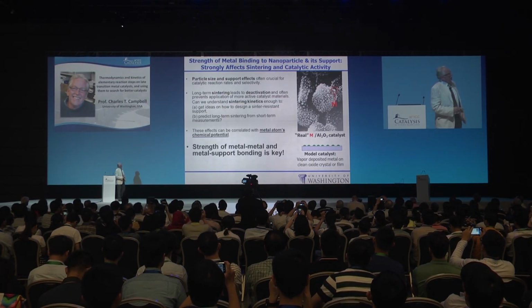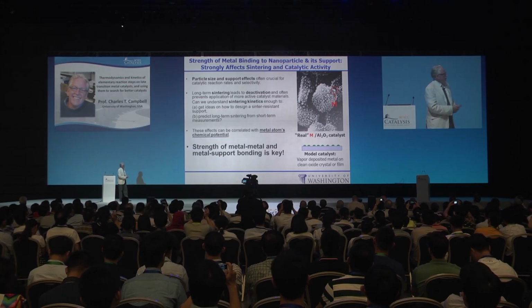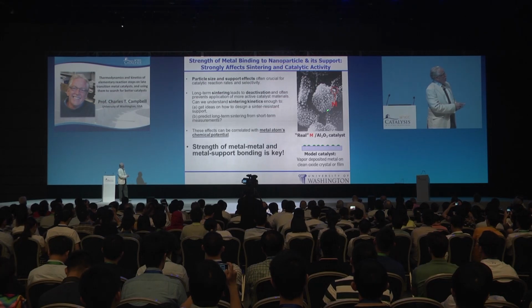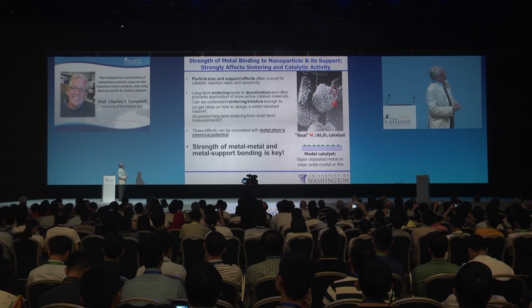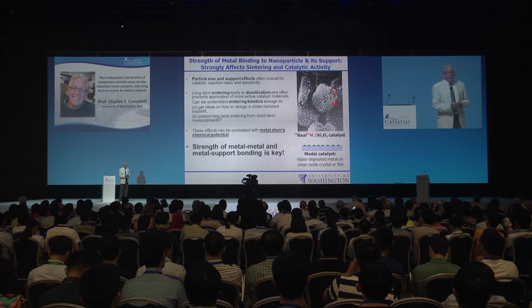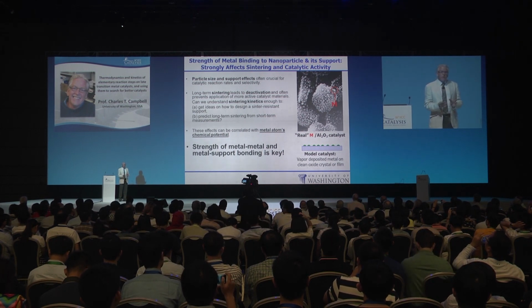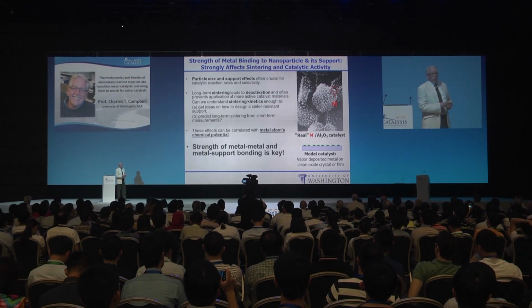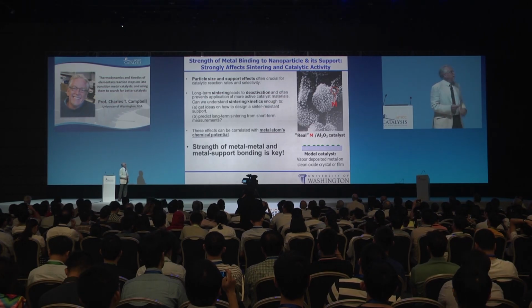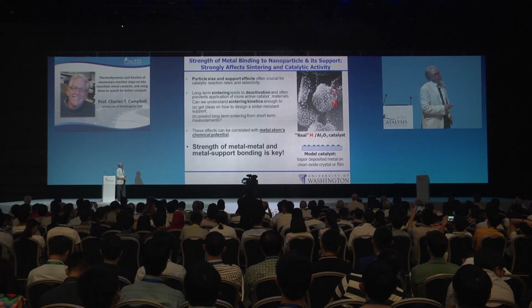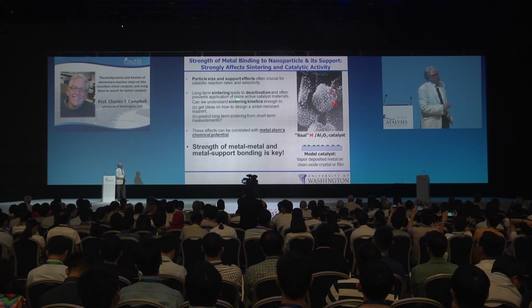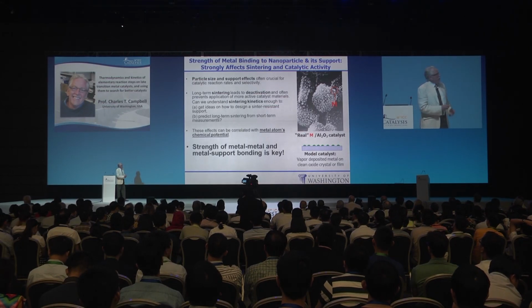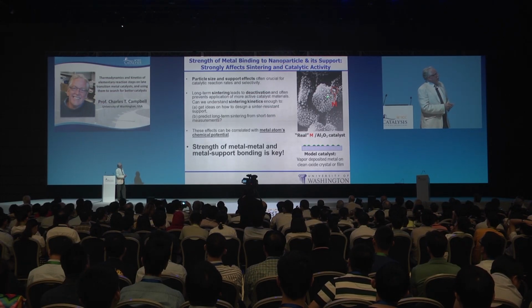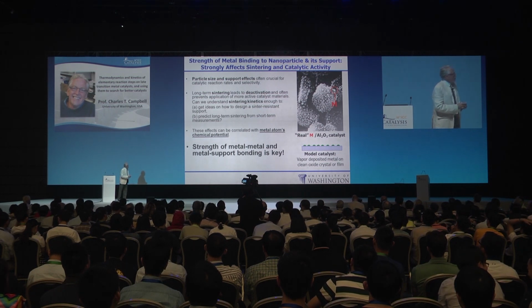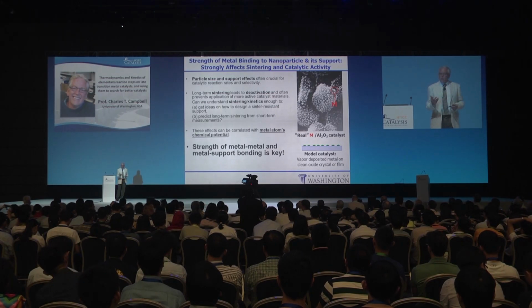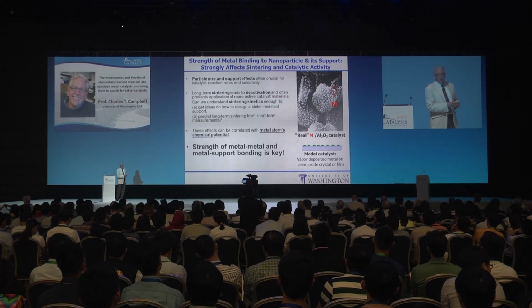So next I'd like to talk about the metal energetics, that is the energetics of the metal atoms in these particles. And of course, a real catalyst has metal nanoparticles supported on oxide or carbon type of a support. And we've heard a lot of talks already in this conference. There are particle size effects when you're below about 6 nanometers in particle size. And there are important support effects that particularly manifest themselves when the particles are in that small size regime. Maintaining active catalysts for long periods of time is important, particularly if you have sintering taking place at the reaction conditions of interest. And I'm going to talk about the energies of these metal atoms and how they impact these types of things. And a key concept there is going to be the concept of the metal atom's chemical potential, which depends on the particle size and the support material upon which the particle sits.